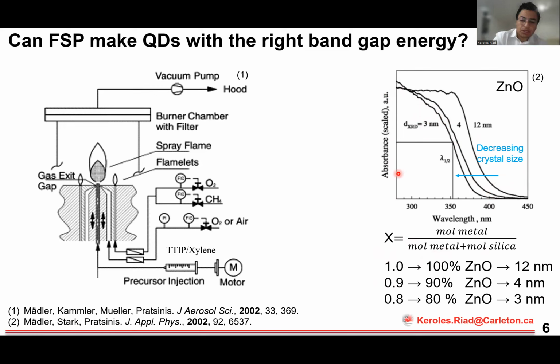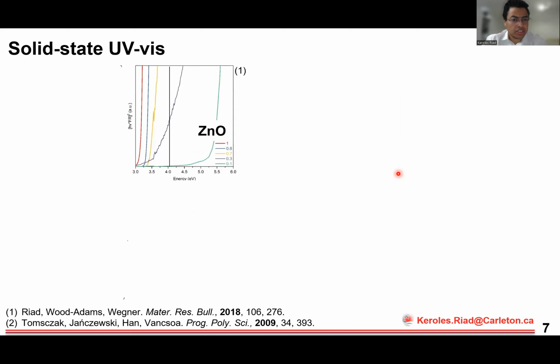So I decided to try to push this further, and here I show Tauc plots, which is the conventional way of reporting band gap energy. In this case, again still with zinc oxide, I push X all the way down to 0.1, which means that it's 10% zinc oxide, 90% silica. And you see the quantized effect here very clearly. The band gap energy plotted on the x-axis increases as X decreases, so the silica loading is increasing. And you clearly see that with X equal 0.1, the zinc oxide quantum dots have a band gap energy well above the 4.1 electron volt threshold that I would like to exceed for my application.